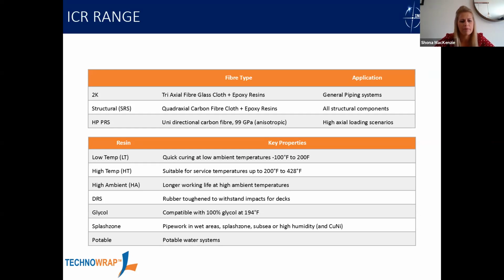So the resin systems themselves: we have the low temperature and high temperature resin. The low temp is a quick curing resin system at low ambient temperatures, and its in-service temperature, as I mentioned previously, was -100 to 200 Fahrenheit. You have the high temperature resin, which is suitable for in-service of 200 Fahrenheit to 428 Fahrenheit, and that does require post-curing or heat in order to cure the resin. We also have a high ambient resin, and again, that just allows for a longer working life, meaning the resin system isn't going to cure off. And it's easier to work with the resin when you've got high ambient conditions.